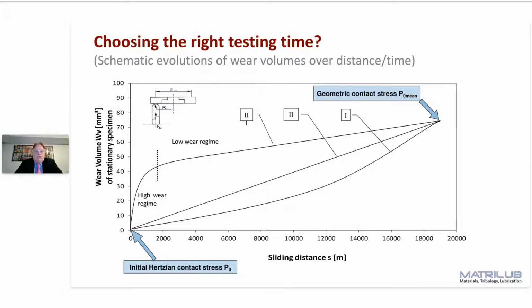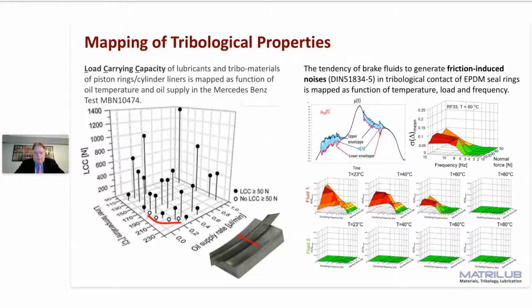You must be really sure that your test was long enough to be in a steady state, so you have the wear rate under the low wear regime, and no longer are you running in or into a high wear regime. So to find the right testing time, I always prefer to have longer testing time and to have more test machines than to have too short testing times, which can really mislead.